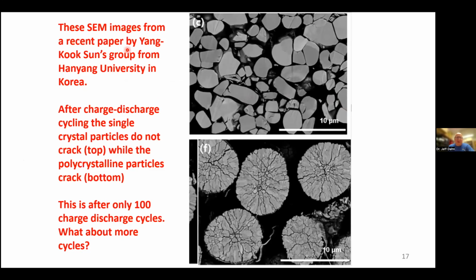So there's a really famous researcher in Korea named Yang-Kook Sun. He's at Hanyang University, and he, among others in the lithium-ion battery community, including myself, are promoting what is called single crystal positive electrode materials. So what he shows here is what happens to the traditional positive electrode materials after 100 charge discharge cycles. You see all this microcracking.